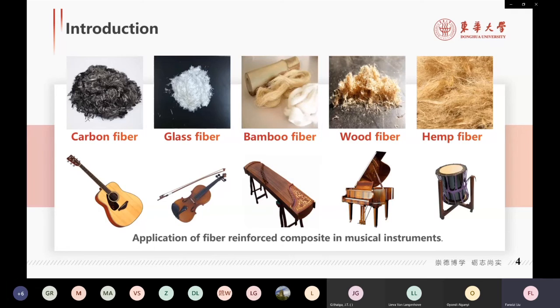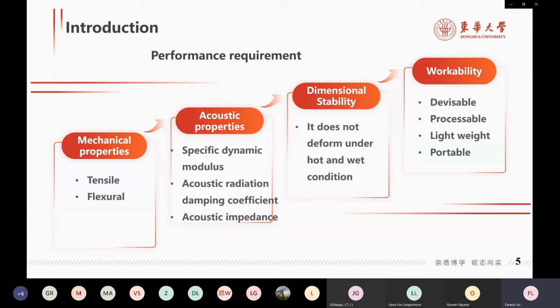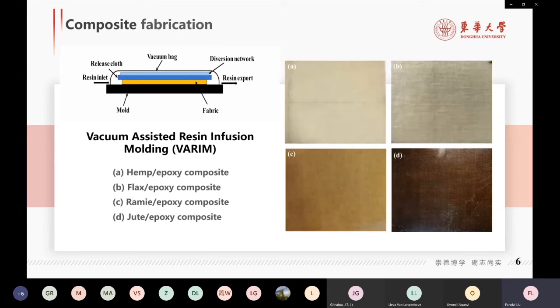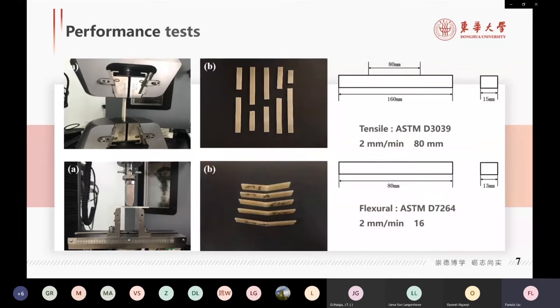Drums need to meet some requirements, such as acoustic properties, dimensional stability, and processability. Especially the acoustic performance, we use three indicators to evaluate it, which I will talk about later. In our studies, four types of epoxy resin composites reinforced with fabrics of hemp, flax, ramie, and jute, respectively, are fabricated using vacuum-assisted resin infusion molding, VARIM. The tensile properties of the composites were tested using a universal testing machine according to the ASTM D3039 standard. The flexural properties test was performed on the same machine according to the ASTM D7264.